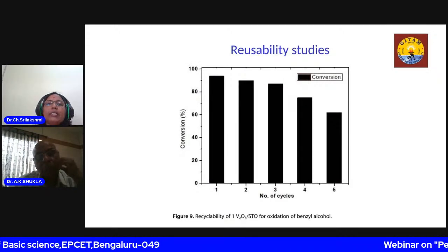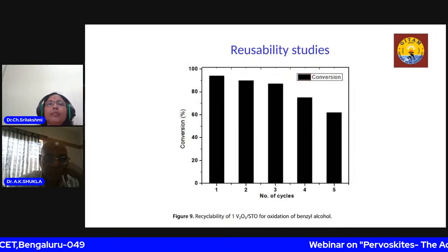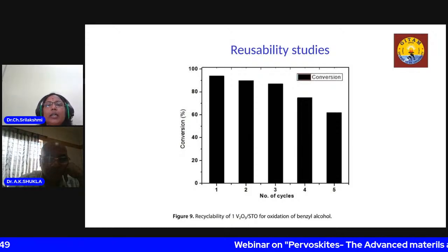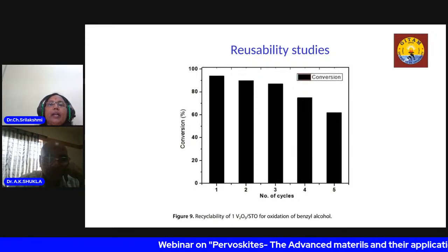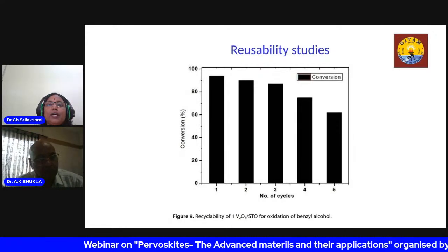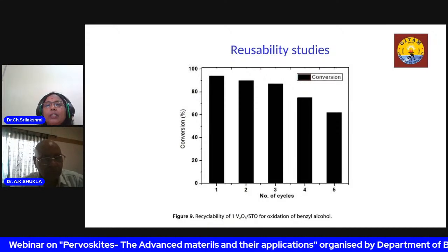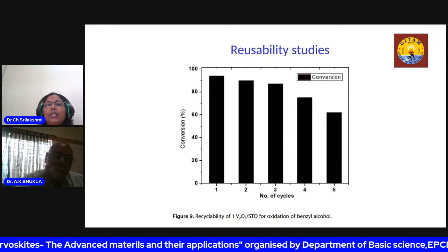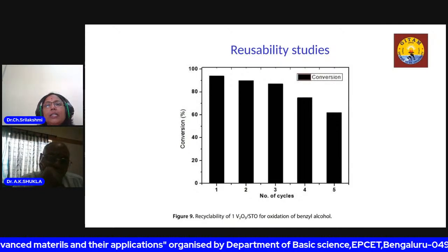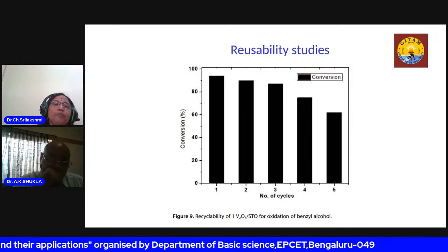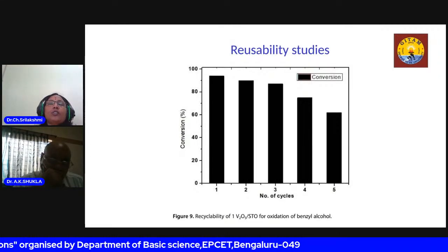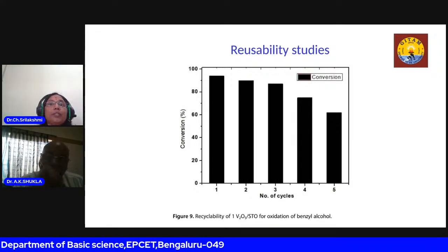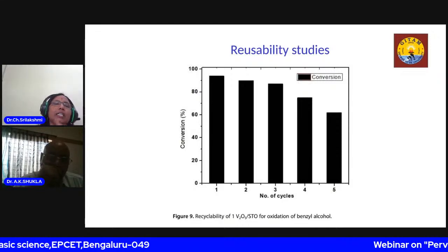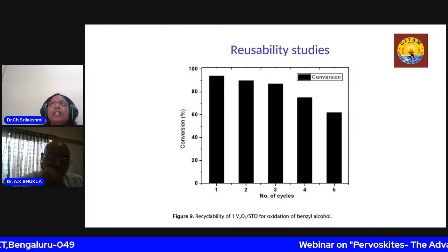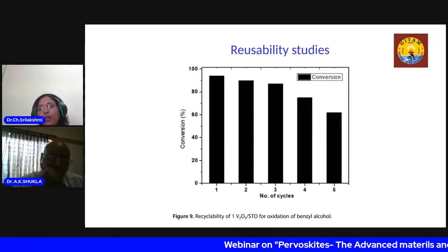And we have also taken 1 weight% vanadium oxide on strontium titanate and tested for recyclability, and it is observed that we can use it a maximum of 3 times without loss in activity. After that, you can see loss in activity takes place. This is due to physical loss of the material, but not the leaching. Leaching is different. Here it is a physical loss of the material because we have taken only 80 mg.